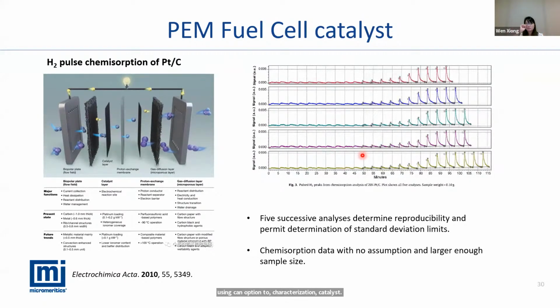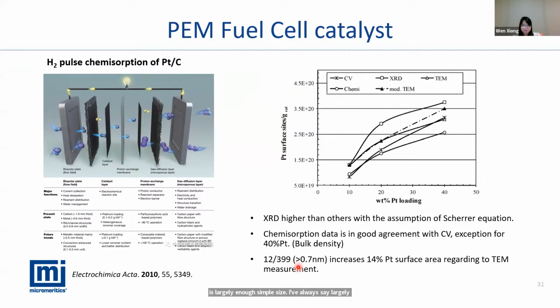The determination of the platinum surface area concentration and the platinum surface area from chemisorption contains no assumption. That's a very, very big advantage of chemisorption. It does no approximation when we're calculating the platinum surface size. The other advantage is a large enough sample size. When we say large enough, we are comparing with the CV test.